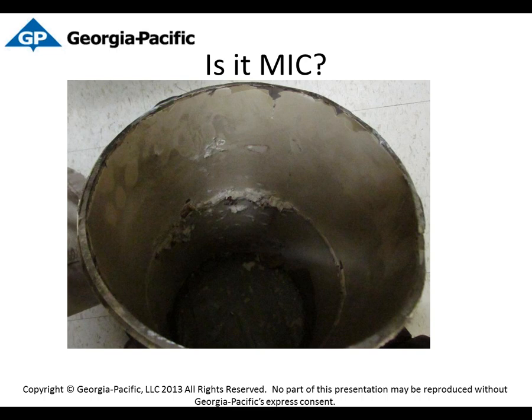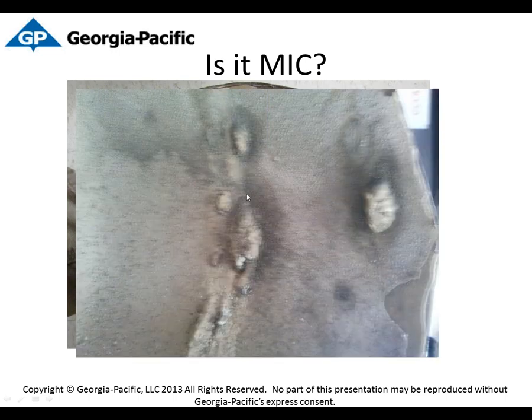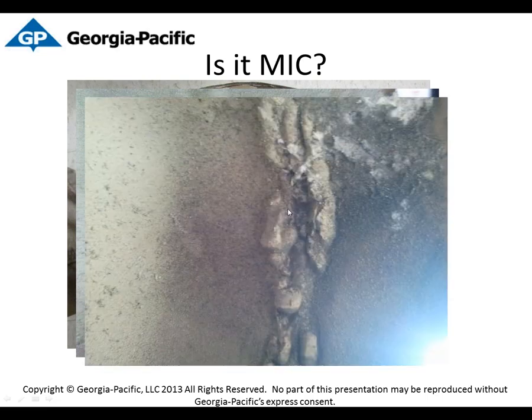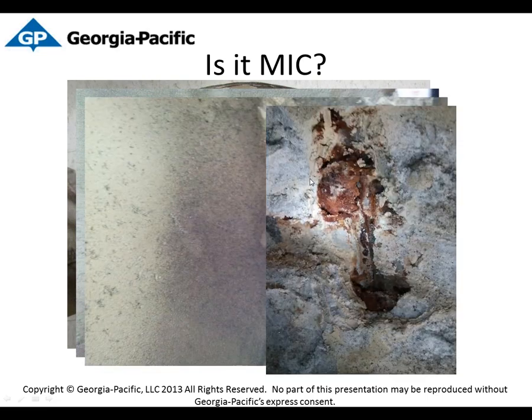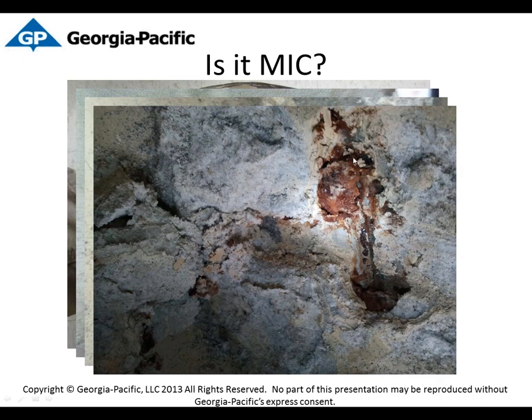And you actually get inside it, and you can see in here actual tubercle growth on the bottom side of the pipe. The rest of this is just hard water scaling. It's a calcium carbonate, what you see as the yellow film here. Here's some tubercle growth along the weld seam. Right along the weld, you have one a little bit farther away from the weld. Again, another weld line right here. And then if we zoom in, this is the actual corrosion of the weld.